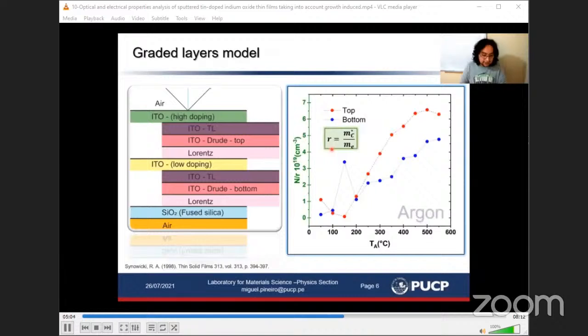the behavior of carrier density divided by a constant, effective mass, for both layers as a function of the annealing temperature. m* is the effective mass divided by the electron mass. For the bottom layer, the blue graphic, the carrier density increased in contrast with the top layer, which decreased, and this is due to the structure being rearranged at the beginning of the annealing, and from 150 degrees centigrade both begin increasing, since the substitution of indium by tin and the creation of oxygen vacancies may be occurring.